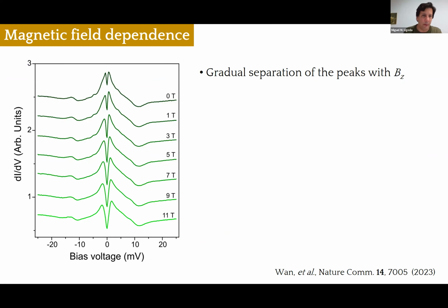Obviously, we have carried out the magnetic field dependence. Here I show you another set taken with the same tip in the same location from 0 Tesla up to 11 Tesla, where you can see that basically nothing changes except for the distance between the two peaks, right? At 0 Tesla it's around 1 milli-electron volt, whereas at 11 Tesla it's a little bit less than 5 milli-electron volts. So there's a gradual separation of the peaks, but nothing else.